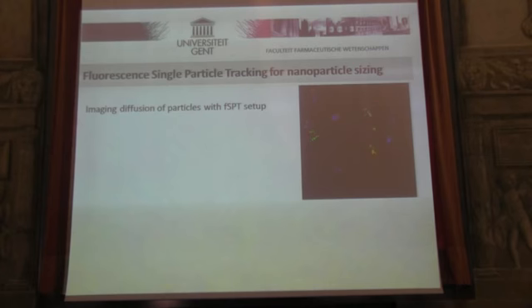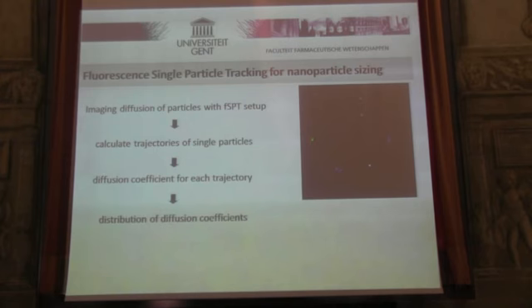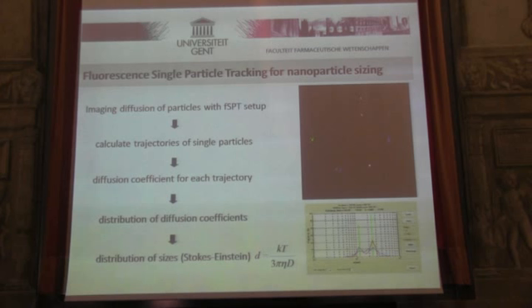And on this movie that you see happening, what you see is nanoparticles dispersed in plasma, and you see the Brownian motion. It's really random, but the thing is we can follow the motion on a particle by particle basis. We can do the tracking. I have to move on with the slide. So we do the calculation of the trajectories, and for each trajectory we can calculate the diffusion coefficient for each particle. If you do this for 1000 particles, you get the distribution of diffusion coefficients, and if you know the viscosity, then you can convert this to a size distribution. It's basically the same as a DLS, a dynamic light scattering instrument, that also measures the diffusion and then converts it to a size distribution.